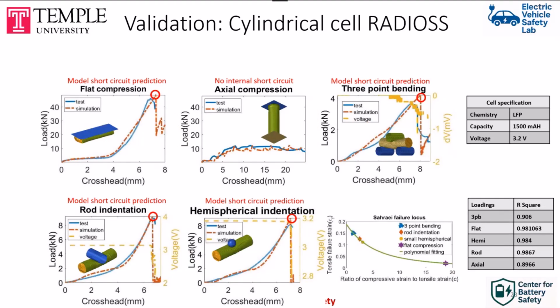Now, this was a pouch cell example. This is a cylindrical cell example. Again, you see for all of the cases with red circles, we predict a short circuit. The one case that we don't predict is the case that in the test also had no short circuit. So this was the validation for the cylindrical cell. We have done at least another cylindrical cell with different chemistry. The first cell was a lithium cobalt chemistry. We also tried a lithium phosphate chemistry. For both of them, we see similar results.